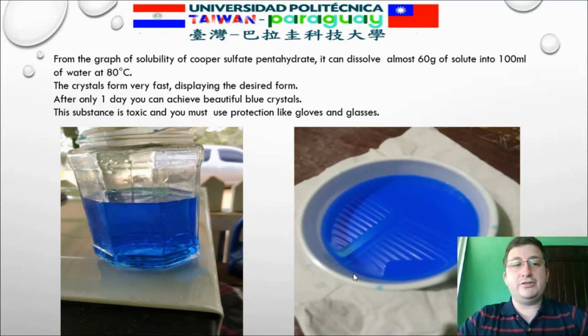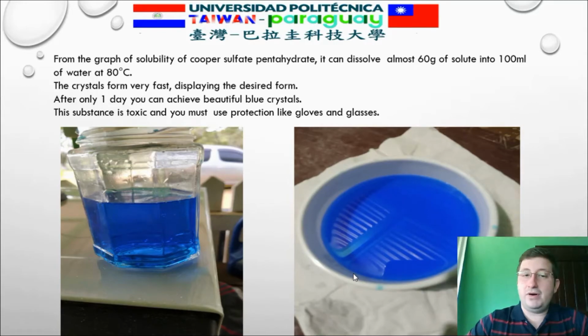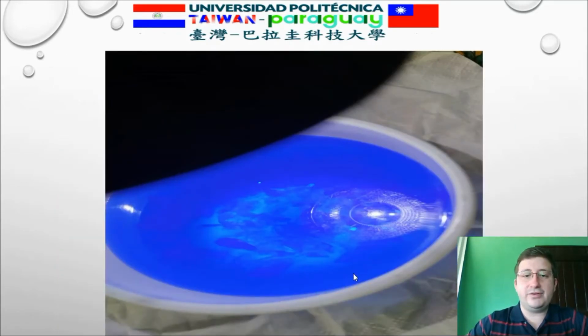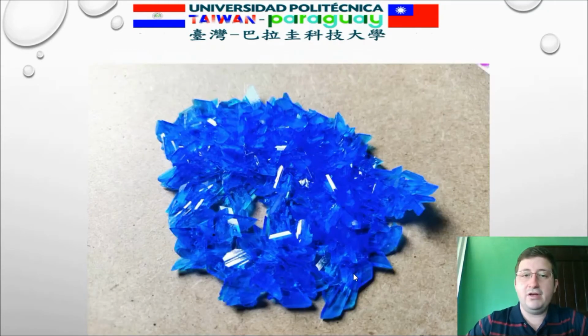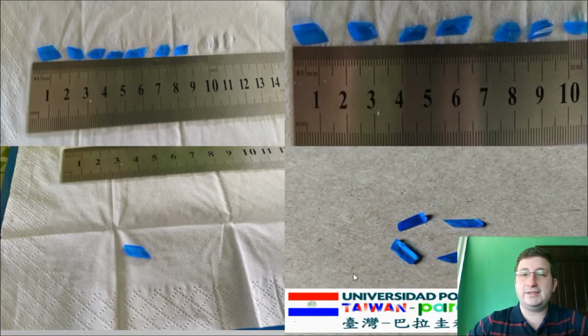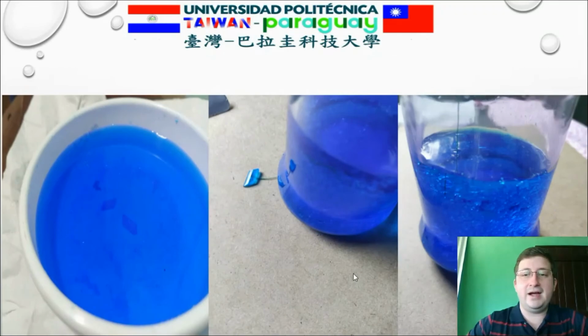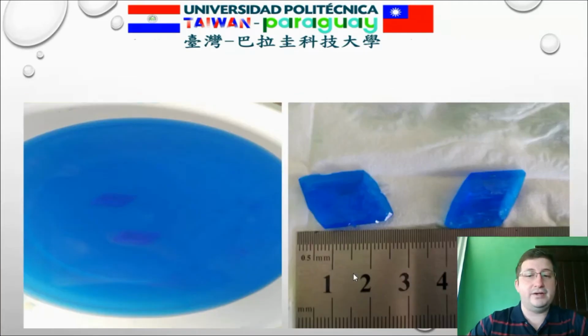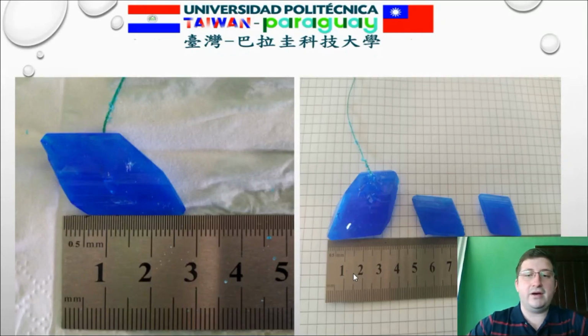The first step is to achieve a supersaturated solution to achieve our first seed crystals. From this supersaturated solution, after a few days, many small crystals form at the bottom of the container. From this polycrystal, I chose the best one as my seed crystal. After that, I glued it to a thread and hung it again into the container. On the other hand, I put some of the crystals at the bottom of the container. After a few days, the crystals increase in size like this. This is my crystal that I put at the bottom of the container. And these are the other crystals. As you can see, it increased its size and it shows a desired shape.